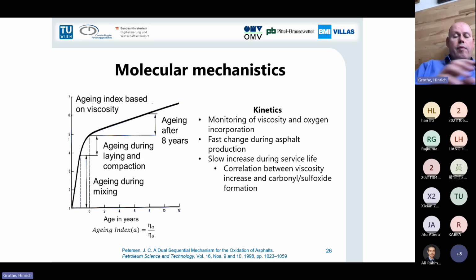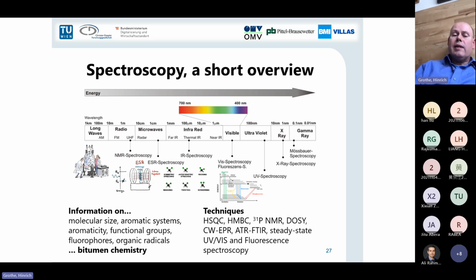So we have fast change during the asphalt production, and we have a slow increase during lifetime and a correlation here between viscosity and time, but as I will show you later, also a correlation between oxidized organic matter, which is mainly carbonyls, but in some cases also sulfoxides formation and time. So how to investigate these changes?